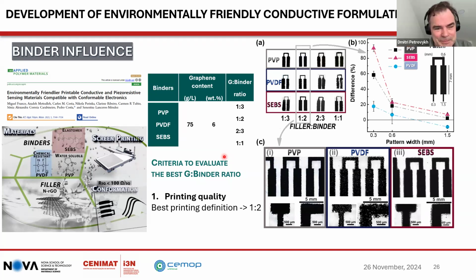Correct. Laser-induced graphene is very interesting because you can achieve very conductive graphene, as there is no binder. The challenge of laser-induced graphene is the adhesion itself. You need to try to stick it. Probably this is the main challenge, to stabilize it, to stick it. Because if you just induce graphene, it tends to easily fall off, easy to escape. So it needs to be well passivated.